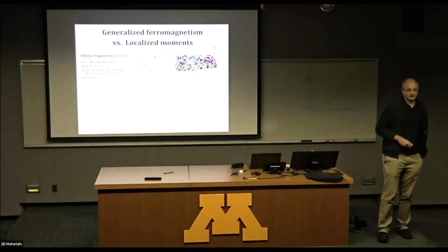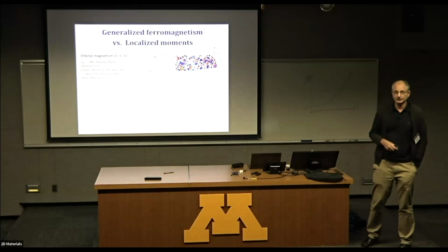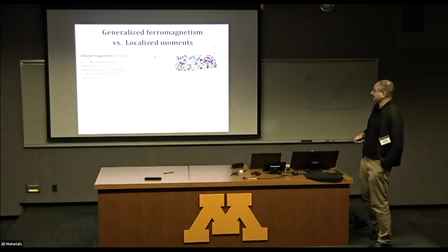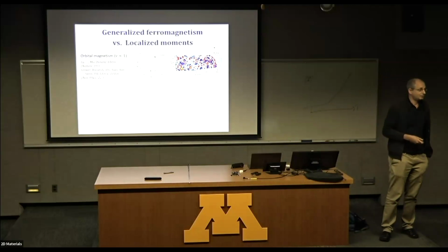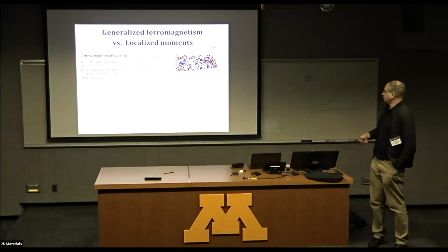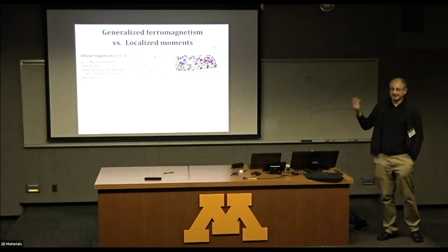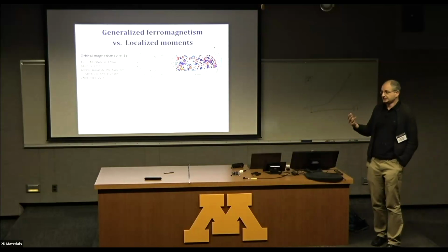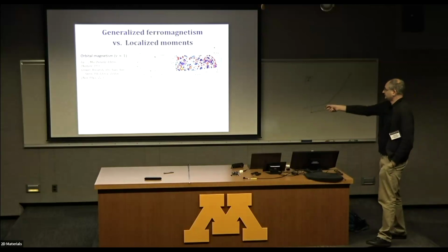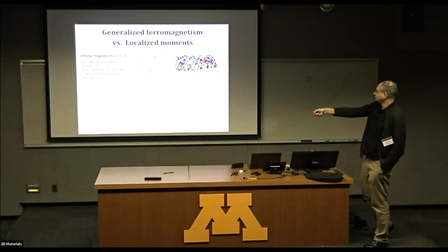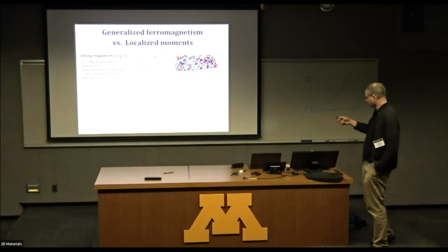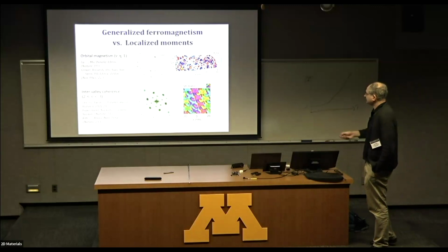So we know that the ground states, as a function of density, over much of the phase diagram realize some kind of generalized ferromagnets. It's not a usual ferromagnet because you have spin and valley and orbital degrees of freedom, so you have to determine how these degeneracies are being lifted. But for instance, close to nu equals 1, there's some kind of spin and orbital ferromagnetism, which was observed in some samples at least.